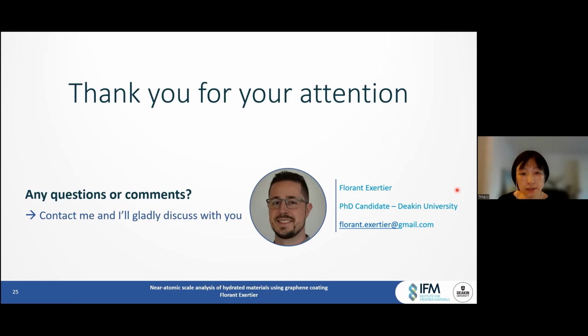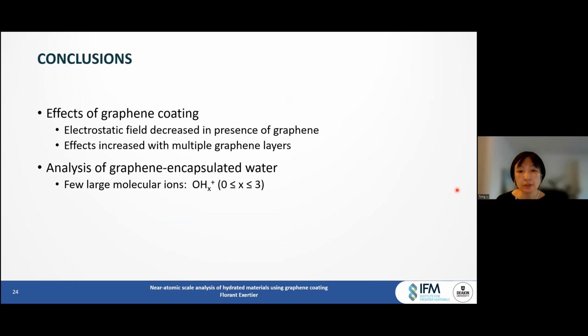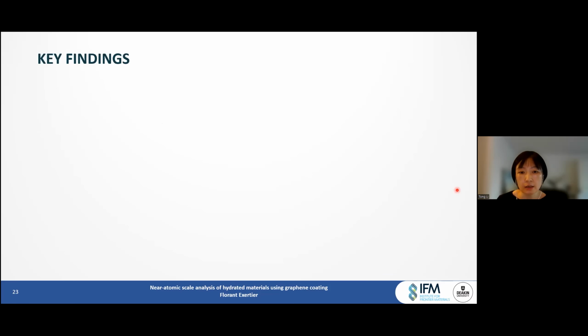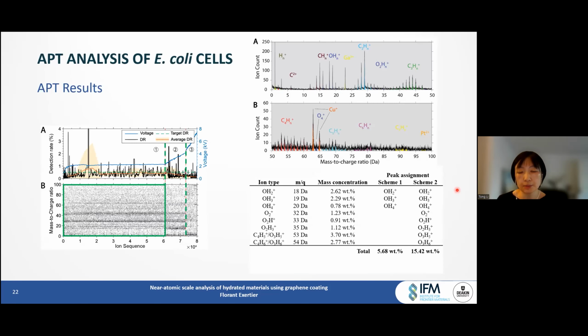So I think this is an exciting study. We are talking about using atom probe to analyze biomaterials. The case you have is E. coli. And if we look at the chemical formula of this molecule, essentially it has a very, very big mass, something like over 800, but the mass spectrum you analyze is mainly species below 100 Da. I'm wondering, how can you make sure the peaks you're analyzing here are from the E. coli, or how did you distinguish that they're not impurities from, say, plunge freezing or the graphene capping?